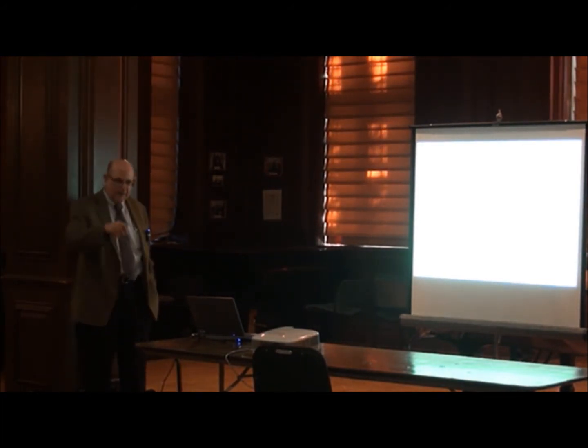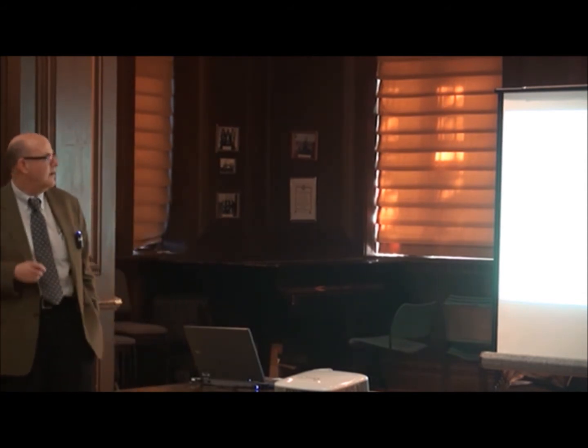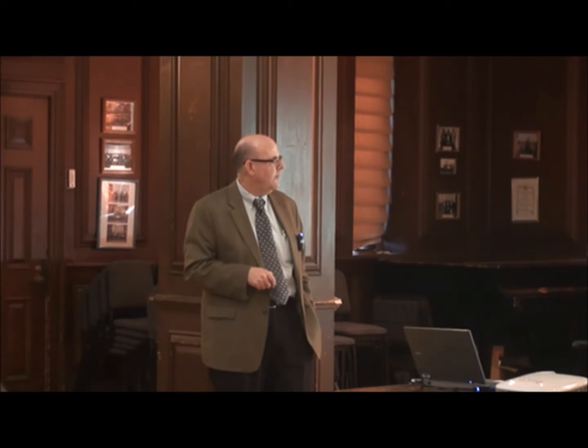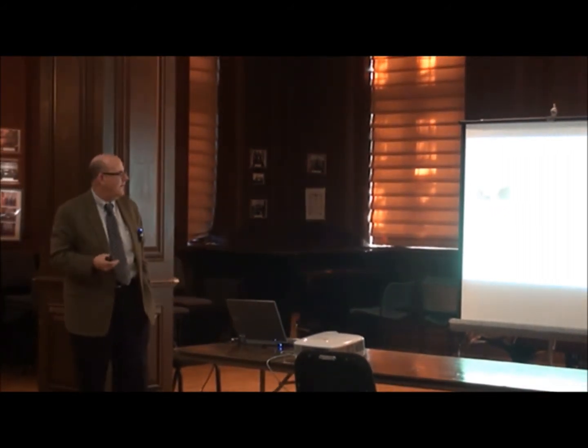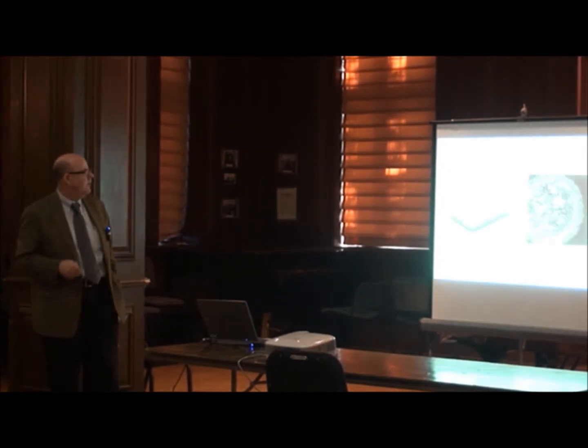Bearing area, I mentioned before, is an example of that, where if I look at a profile and I cut through that surface, I look at the area of contact that I would make and I graph that. And then from this bearing area curve, I can get an idea of how high the peak heights are, how deep the valley depths are, and also a measure of the effective area of contact. So when I look at a surface that might be used inside an engine block, for example, that's a particularly designed surface, usually a cross-hatched honed surface, I get this bearing curve, which is really a plot of the percentage of area that I would bear against as a function of height. So as I wear down on that surface until I get to the right area of contact to support the load, that's where the system will behave.